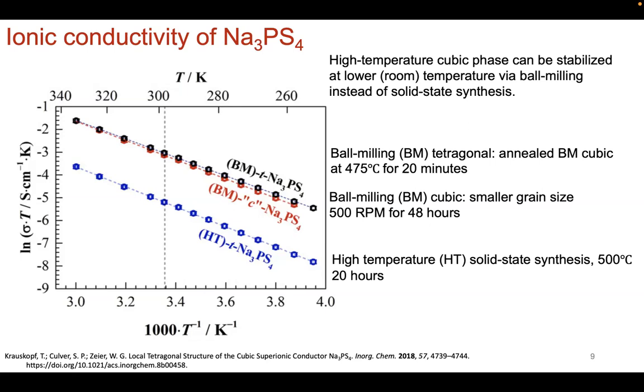So one has to wonder, what is the origin? How do you have similar performance for the tetragonal phase and also for a cubic phase when our underlying hypothesis was that the cubic phase has higher ion conductivity than the tetragonal phase? Clearly there is some similarity in the crystal structure of the material that's driving the ion conductivity to result in pretty similar numbers. If the claim is the average structure is one is cubic, the other is tetragonal, then they should result in different numbers.